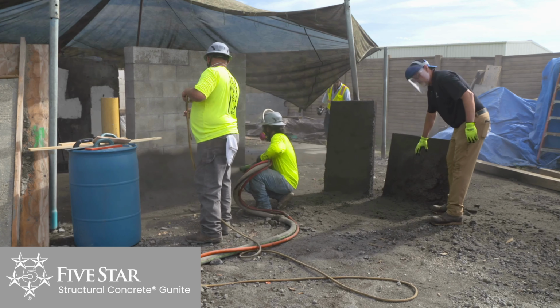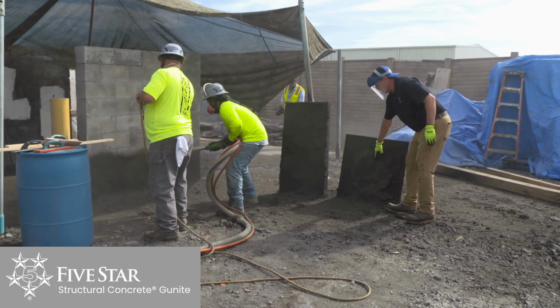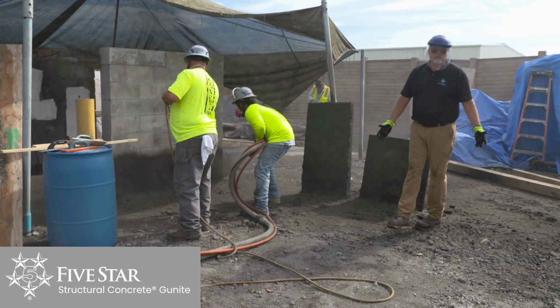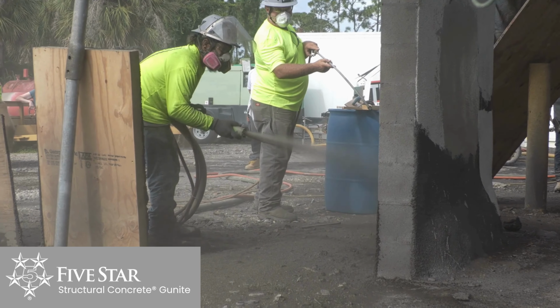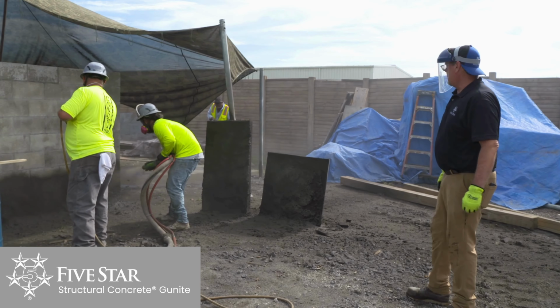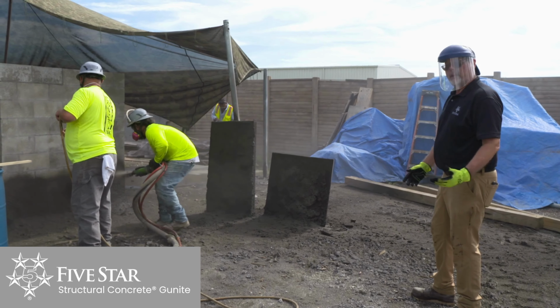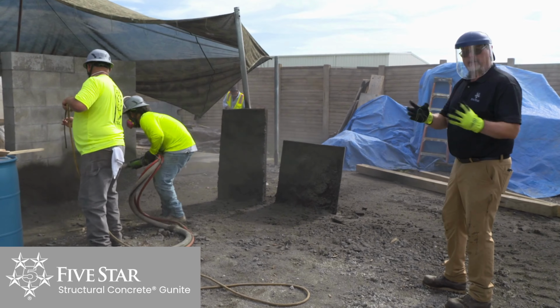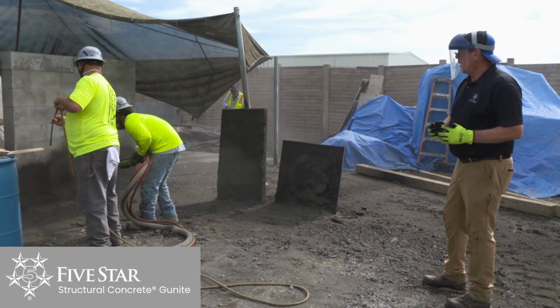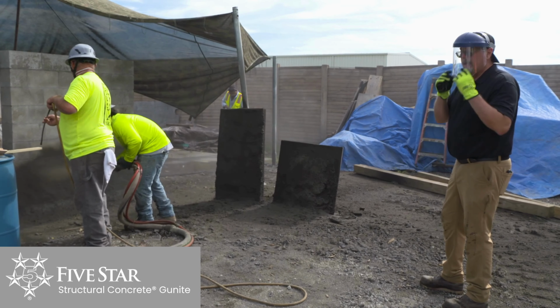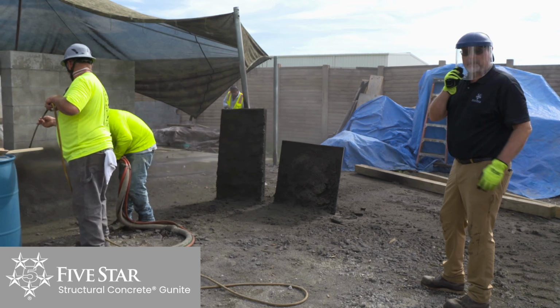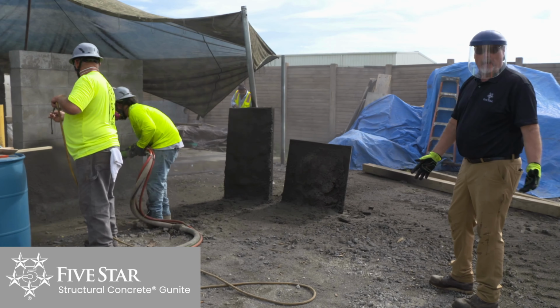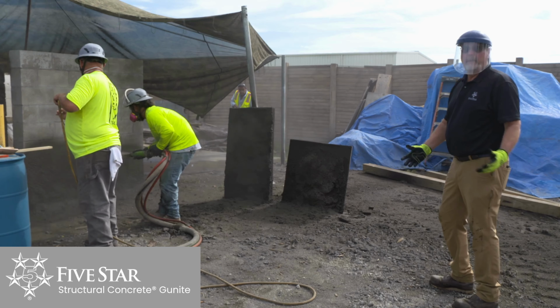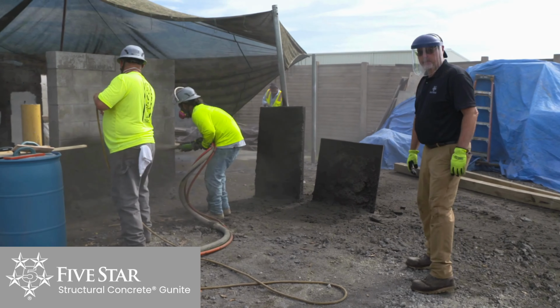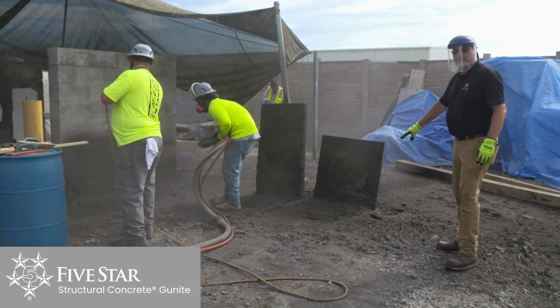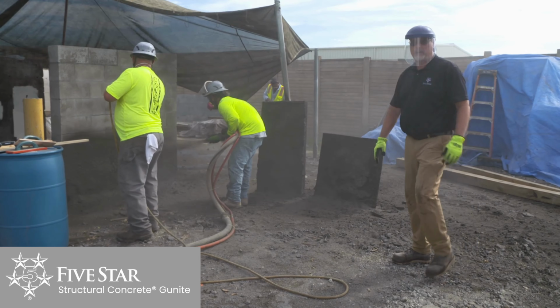You saw from the test panel how hard it is already, and that's the beauty of this material. The material is curing out now and gaining bond strength and gaining compressive strength. It's expelling the water that's inherent in the mix at a very fast rate. When it gets below 5.5% moisture, a coating can be applied. Now the coating can be applied per the coating manufacturer's recommendation, but it'll be less than 5% in probably about a half an hour or so.